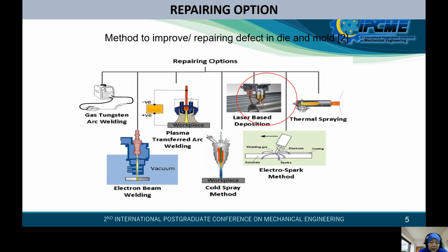Die wear and failure significantly affect the service life of die, resulting in the need for a new die, which is usually expensive and unexpected high production cost. Figure show option method to improve or repairing defect in die and mold. The method is gas tungsten arc welding, electron beam welding, plasma transferred arc welding, cold spray method, laser based deposition, electro spark method, and thermal spraying. But this topic just focus on laser based deposition method. The laser technique is laser cladding.